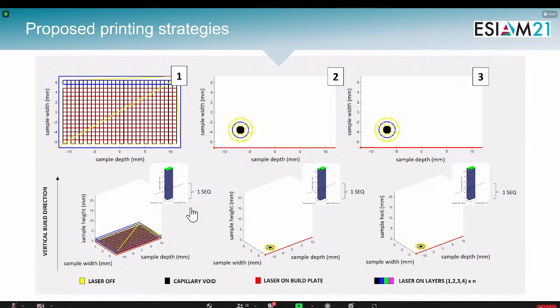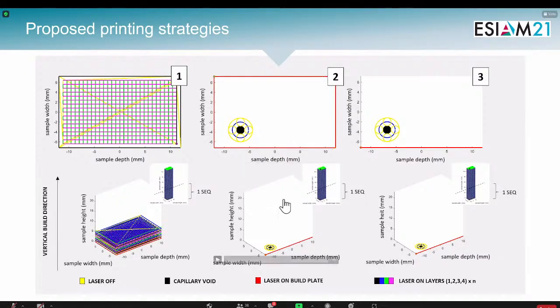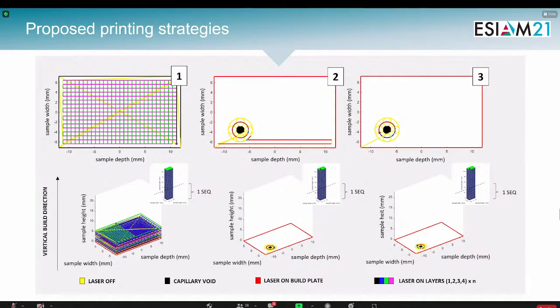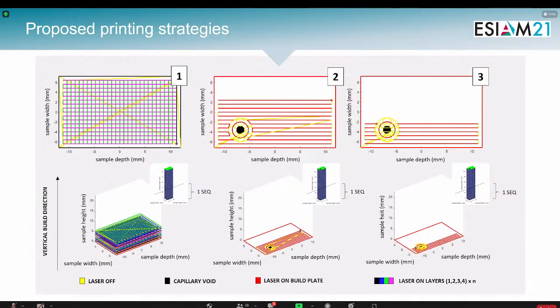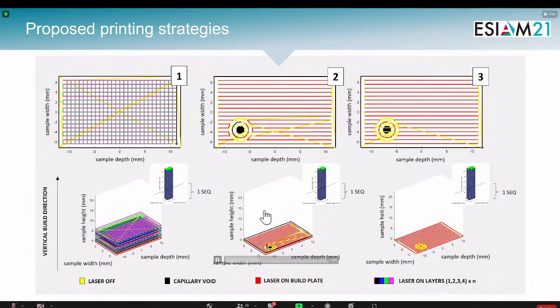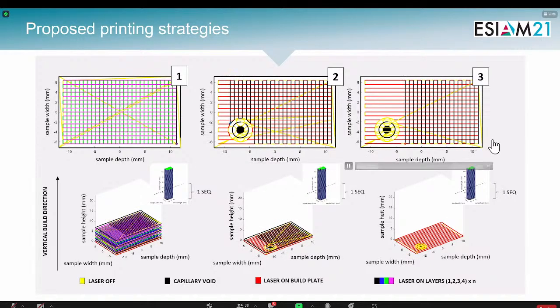And so the printing trajectories that are given as inputs to the machine were coded in MATLAB. The first strategy relies on printing the first sequence of n layers of the sample, and then subsequently milling the contour and the top surface of these first n layers, drilling a hole through these n layers, and then continuing following the next sequences till reaching the final height of the sample. The 2 other printing strategies rely on the consideration of the capillary directly in the printing trajectory, and this will have different effects on the residual stresses and the cooling rates during the printing process, but also on the geometrical accuracy that can be reached. So these 3 are analyzed.